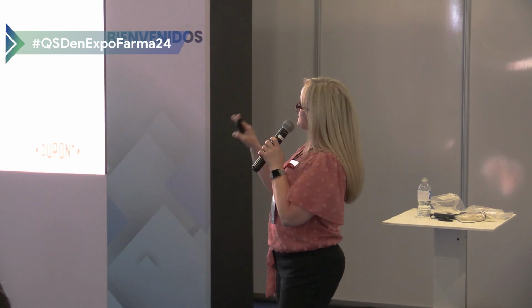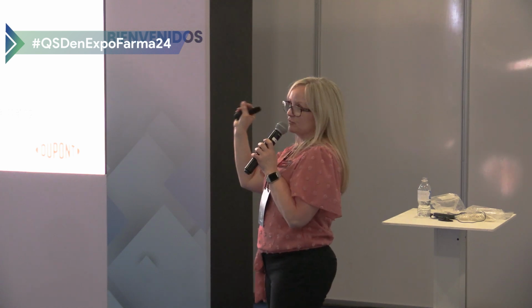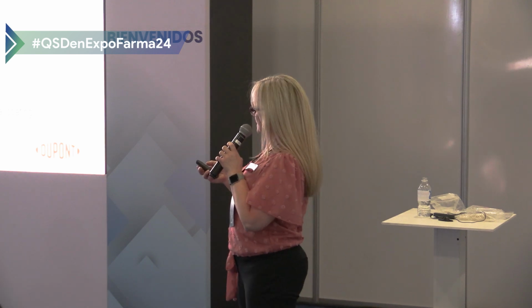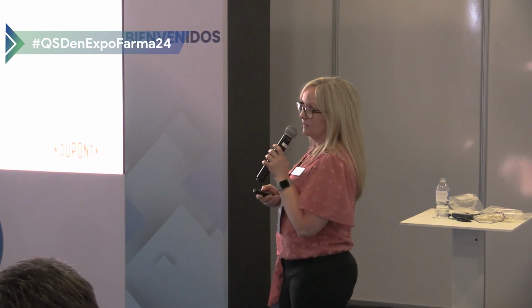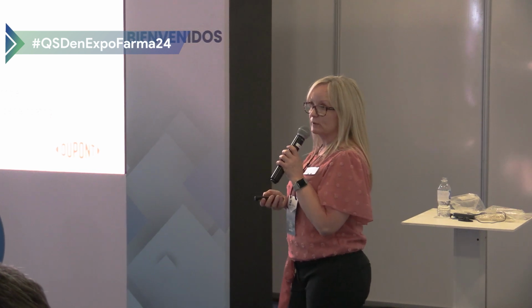So again, here are the processing steps for a PSA. You can see it's very like the SSA process. The only difference is you only have one vat of material, and that feeds directly onto the line and then is coated to the proper thickness that you need. And with these solvent PSAs, the one thing is they do require right now a fluorinated release liner. We're looking into different ones with all of the things out there regarding PFAS. So some of these are not being made anymore, so we are looking at different ones. But it is a bit more expensive than polyethylene or polypropylene like with the SSAs.